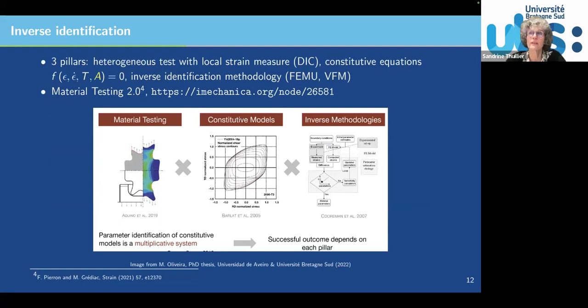In this case, you don't have a direct closed-form analytical expression relating strain and load to the stress and strain. So you will need finite element analysis and an inverse methodology in order to determine the material parameters from the output of your test. Classically, I would say that nowadays there are mainly 2 methods. They are not the only ones, but I would say that these 2 are the most used: finite element model updating, FEMU, and VFM, virtual field methods. In these two cases, this is inverse identification.